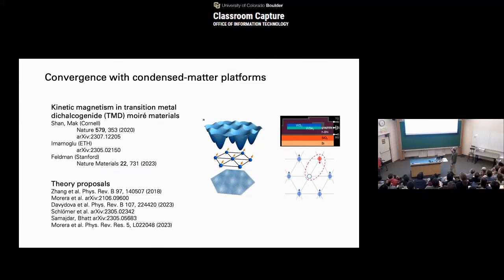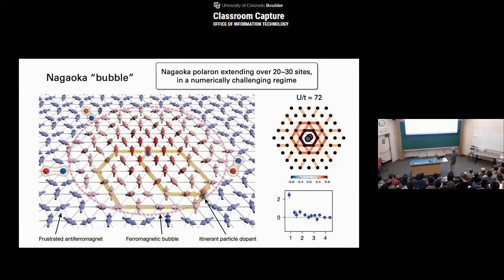As I said, the nice thing is it links to some recent condensed matter research with twisted bilayer materials, where you see similar ferromagnetism, or they claim that they also have kinetic magnetism. It's a bit unclear if it's Nagaoka, but the interaction is very strong. So this may indeed be Nagaoka magnetism in the real material. But also, it's very difficult to compute things. For example, the regime in which we do the measurement here, the theory people can only do at about twice the temperature that we have. At the current temperatures we have, you can only do a system that is significantly smaller than our experimental system. And so this is really getting into a regime where it's really hard to compute things, even with the most sophisticated numerics methods. But we can do these quantum simulations. And so it's a nice example for how we can play with the system.